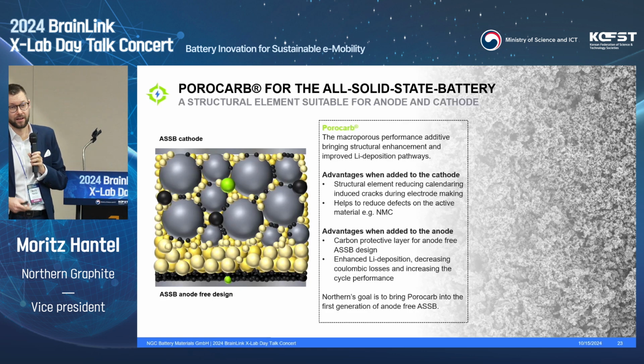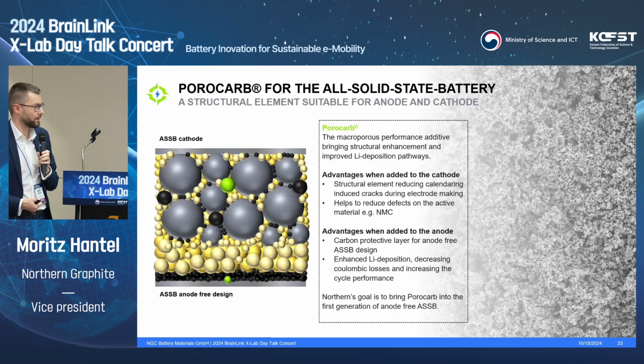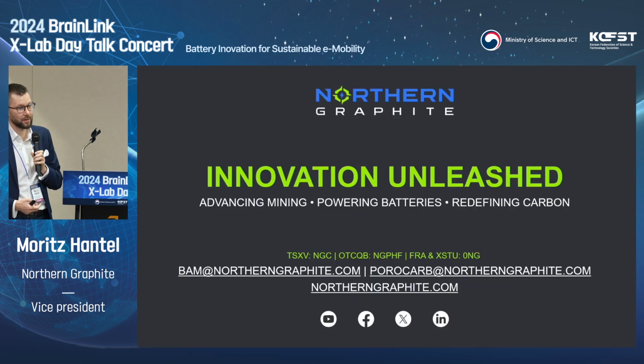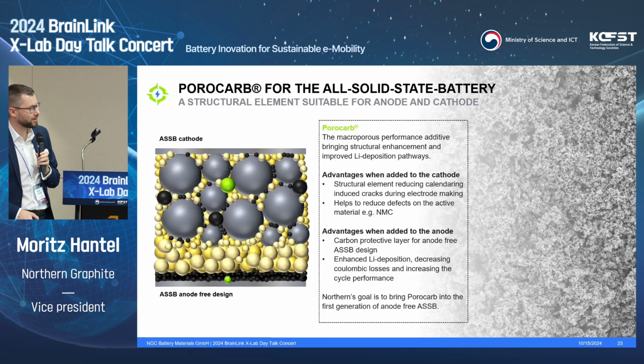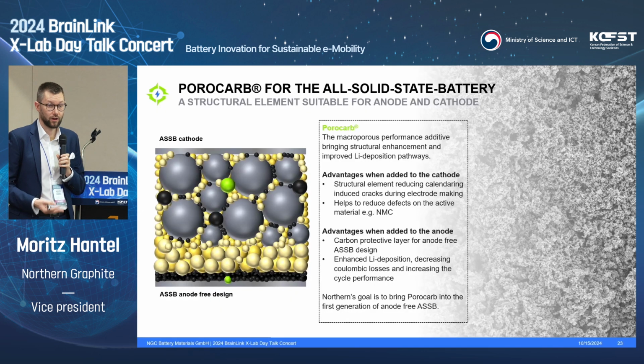looking on the anode side, especially in this anode-free design, typically a carbon protective layer is applied between the solid electrolyte and the current collector. And here the unique properties of porocarb, with its porosity and also microporosity, help with the lithium diffusion. So what we see with customers is that applying porocarb instead of a classical carbon additive, they enhance this lithium deposition in the charging process and decrease their first cycle losses and overall enhance their performance both in discharge but also in cycle performance direction.